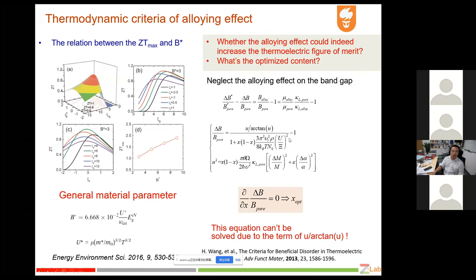And finally, we try to discuss what we call the thermodynamic criteria of the alloying effect. Generally, we can say that the appearance of magnesium vacancy, that is a kind of alloying effect, significantly reduces the lattice thermal conductivity. However, there is generally the question of whether the alloying effect could really increase the figure of merit and what the optimized content is.